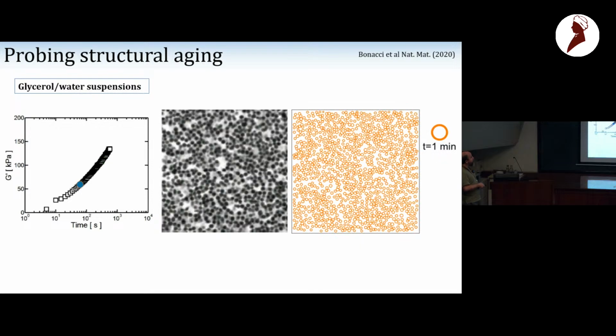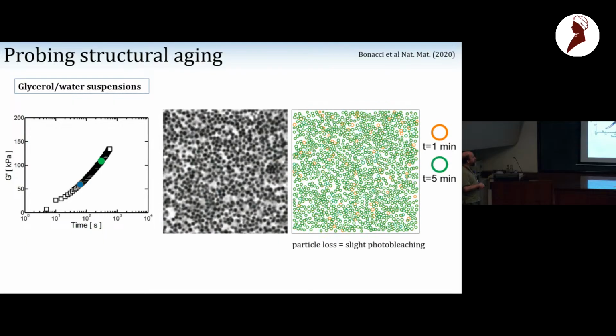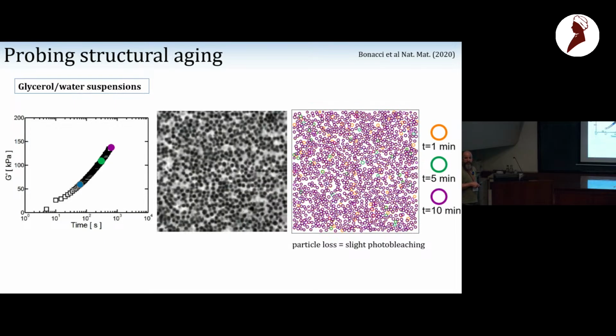So now you see 1 minute, 5 minutes, and you see some particles are here, but what happens is that you have a bit of photo bleaching, and so you lose track of some particles. But the particles that you can keep track of don't move. And you can look at the later time, and again, the particles you can keep track of over 10 minutes, they don't move. But the modulus ages. So now you have something which is not what we hoped to find, that we have aging and we have no structural dynamics.